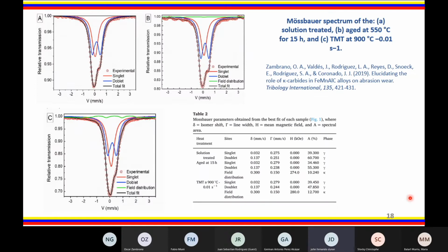In Zambrano's research, Mössbauer spectroscopy has been used to characterize kappa carbides in FeMnAlC alloys. The kappa carbides have a magnetic behavior, where sextet or field distribution are observed, while austenite has a paramagnetic behavior, where singlet or doublet are observed.